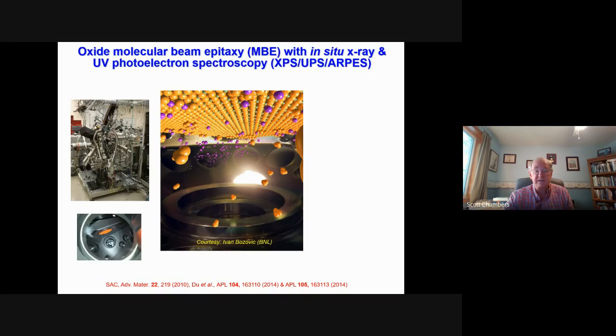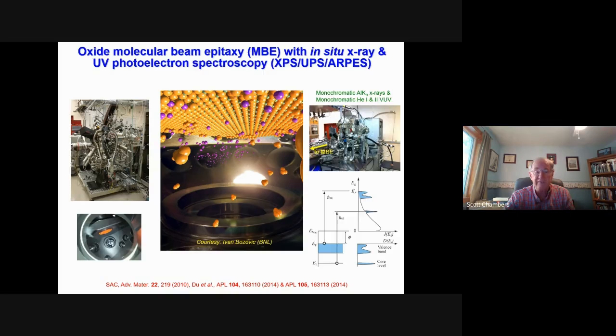The way XPS figures into this is that we have, coupled to our MBE chambers, photoemission chambers, and in this particular case, this is the one that's coupled to this MBE chamber. And so it has two different light sources on it, a monochromatic aluminum K alpha X-ray source, and then a monochromatic helium-1 or helium-2 vacuum ultraviolet source.